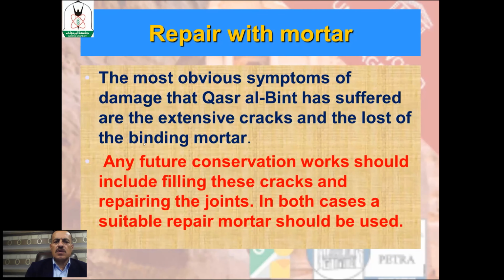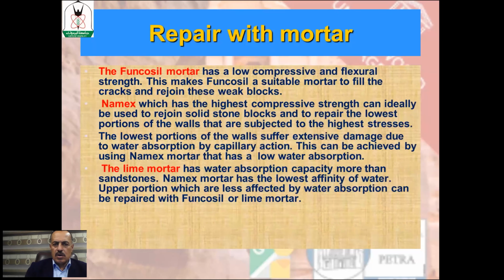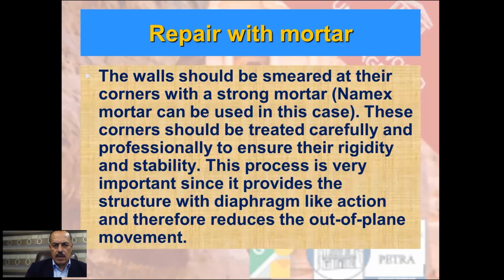The extensive cracks and loss of the binding mortar is really observed as the most obvious symptom of damage of Qasr al-Bint. So we need to use a suitable repair mortar in this case. So here we propose the use of different mortar formulations. The tested mortars proved to be useful, but at different locations and for different repair aims. So sometimes we use Namex, sometimes we use lime mortar. It's really a combination of different mortars that is proposed.